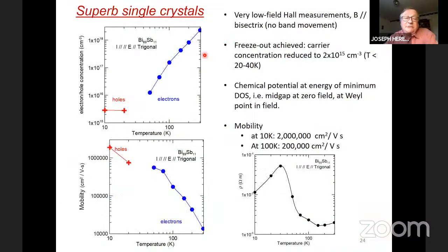Here is one of the mobility plots, very low magnetic field measurements of the electron and hole populations. We see electron mobility start at 20,000 at room temperature, climb to 700,000. The sample actually flips sign here in the Hall effect, and the holes show up here, but they are at the 10^15 carrier concentration range, and the mobility is here in 2 million at 10 Kelvin.